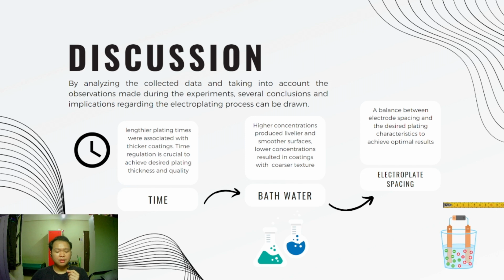The method conducted within 30 minutes resulted in heavier mass when compared, but the method with 10 minutes of immersion showed a more uniform and smoother coating. This proves to us that time regulation is significant when it comes to electroplating.